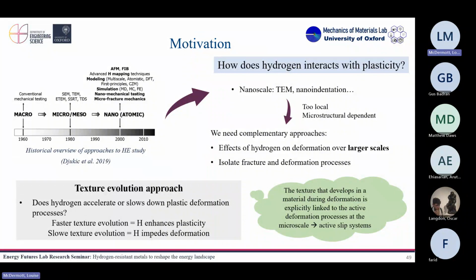I'm not sure how familiar you are with this, but basically, if a material has texture, it means that its grains have preferential orientations, okay? And this development of texture, or of preferential orientations in a grain, is directly related to the active deformation process that's taking place in the material. So basically the slip systems that are active or the slip systems that are not. So really studying how hydrogen affects texture evolution can give you information on how hydrogen affects plasticity.